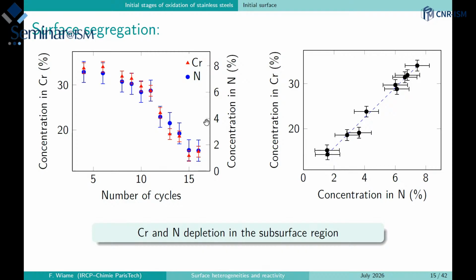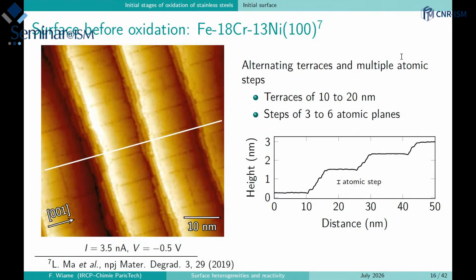Here, for example, you can see that if you increase the number of sputtering and annealing cycles, then you will have a depletion of the chromium and the nitrogen at the surface, which is following the same tendency with the number of cycles. And again, the composition is never the one corresponding to the bulk material. So this heterogeneity of composition, we will see, will have a large influence on the reactivity of the material.